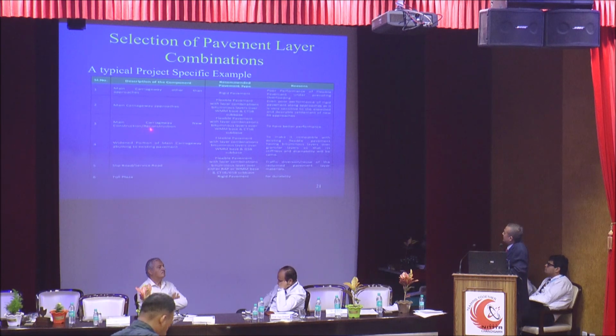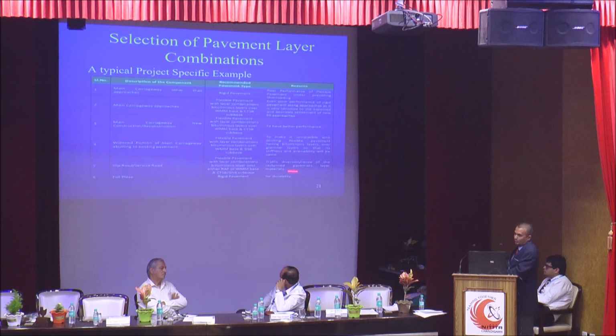Main carriageway new construction, reconstruction, CTSB layer, and main carriageway widening, we have gone for this WMM, GSB conventional combination to make it compatible with the existing pavement layers. Slip road, service road, we have gone for a 3-layer combination, conventional, RAP, WMM, CTSB, GSB, so that we can reuse the RAP generated. Toll plaza, for durability consideration, we have gone for rigid pavement. So, dear friends, there is no cookbook available that describes which layer to select. You have to use your engineering judgment and experience.